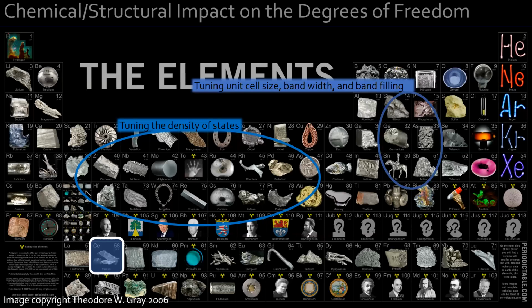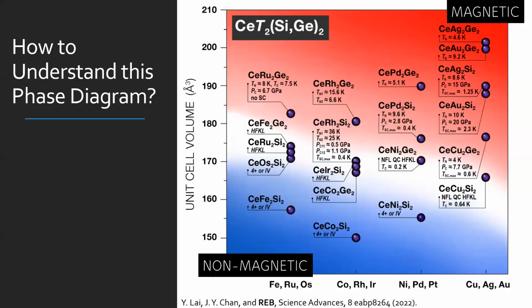Okay, well, just a little bit more about this, putting the chemistry hat back on and not thinking too deeply. What are we doing when we change along the d electron axis? Well, maybe what we're mainly doing is tuning the density of states. What are we doing on the p block? Well, here, we can do a little bit of shell filling if we go this way, or we can change the unit cell volume going this way. And that all maps pretty nicely back onto this, right?